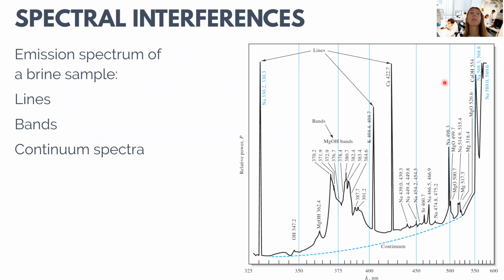So let's see that on the example of a brine sample. Here we can see in the brine sample very nice lines, for example for sodium at 330 nanometers, for calcium at 422.7 nanometers, or for potassium here. But we also see bands. For example, this is a band for a molecular species, a magnesium hydroxide complex. So this is not an atom, it's a molecular species, and we see that it's forming a very broad peak here.